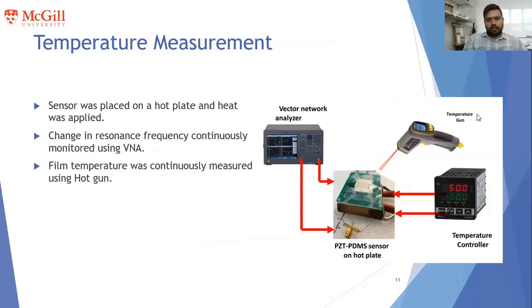And here is the setup of our temperature measurement. As you can see, our sensor is placed on a hot plate, whose temperature is controlled using a temperature controller. The PZT PDMS film's temperature was continuously monitored using a temperature gun, and the S12 response of the film is continuously monitored using the VNA.